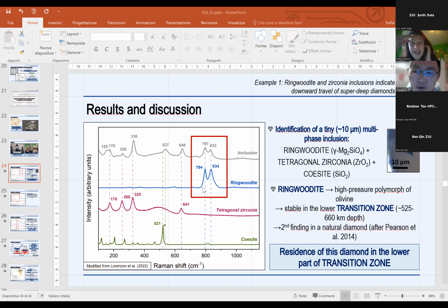As a function of the application of the tetragonal zirconia, people synthesize tetragonal zirconia with different chemical impurities, and as a function of this, the Raman spectrum changes. But before this finding, we didn't have any natural example of tetragonal zirconia, and consequently we didn't have any example of a Raman spectrum of a natural tetragonal zirconia to compare with our diamond. In addition, we must consider that tetragonal zirconia is the most probable phase present in this multi-phase inclusion.